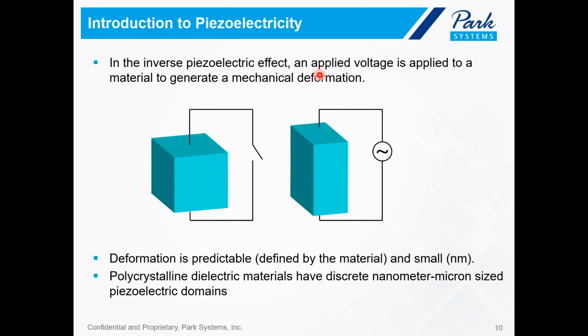So these piezoelectric materials have predictable deformation once a bias is applied, and one can use equations to convert the applied electrical voltage to piezoelectric response. And the deformation of the sample is not only predictable, but tends to be quite small, mostly in the nanometer regime. Also, polycrystalline dielectric materials have discrete piezoelectric domains, and these are on the nanometer and potentially micron size scale. So you can imagine that this can be quite challenging to characterize, because you have nanometer or micron size domains, and the deformations are very small, mainly in the nanometer regime.